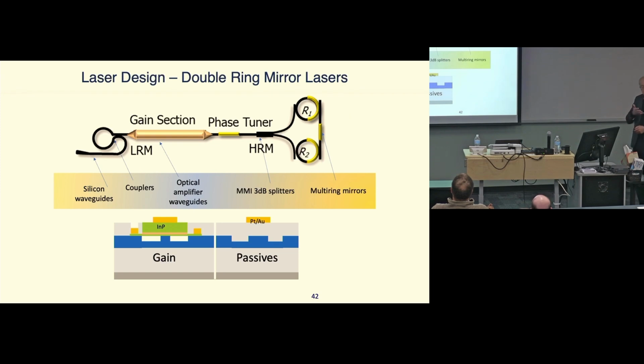So our standard workhorse for all these things, visible to infrared lasers, has 2 rings, and the rings have slightly different diameter. So the light comes in, goes around both of these cavities, comes back out again. Then you have a gain section, a phase tuner, and on the other end we have a loop mirror. As you change the kappa of this coupler, the output coupling goes from 0 to 100%. It's really nice to have a tunable knob there that allows you to change how much power you get out. And obviously, high power out also means more noise in the cavity. So there's a trade-off between noise and power.